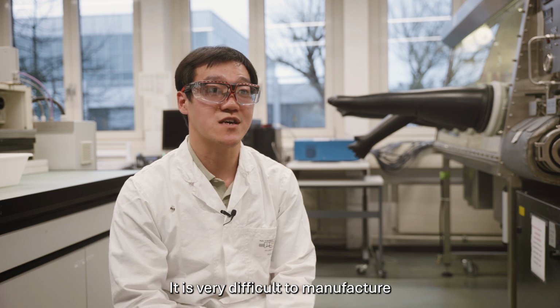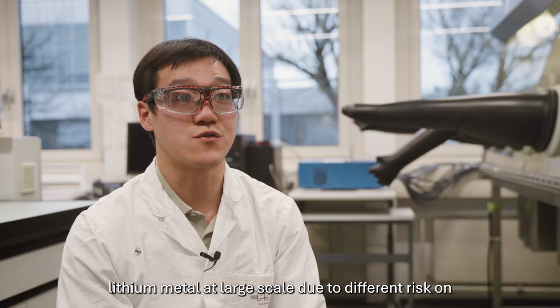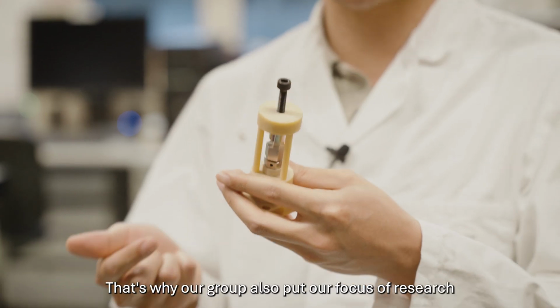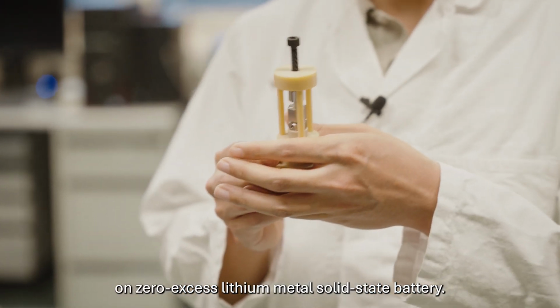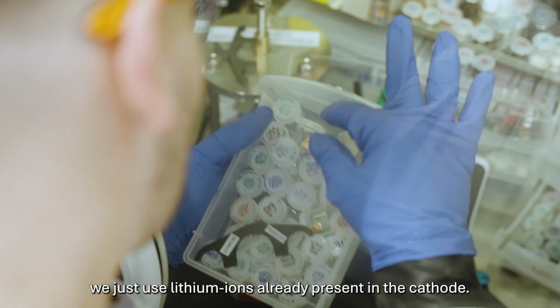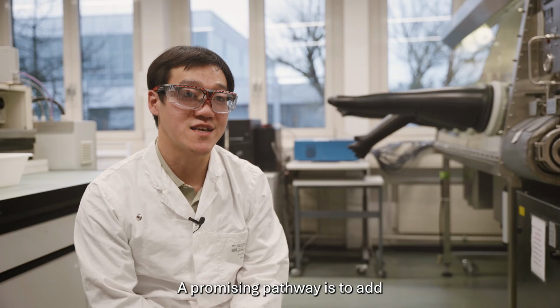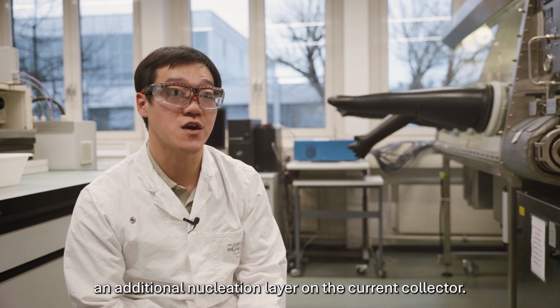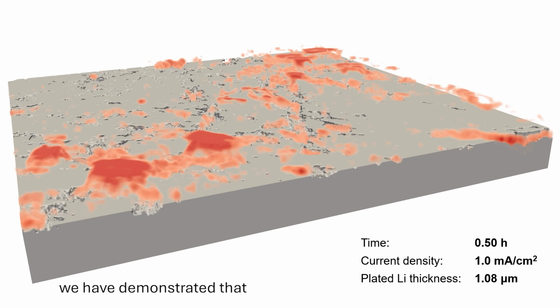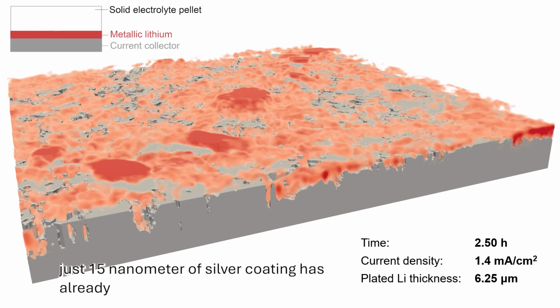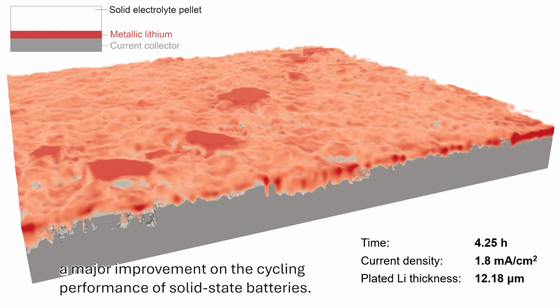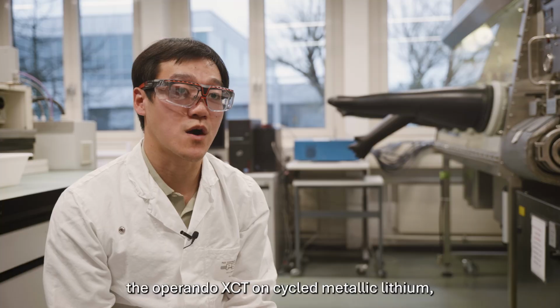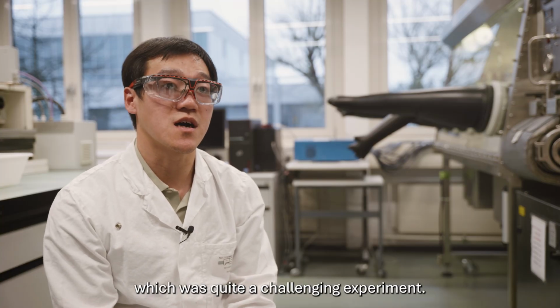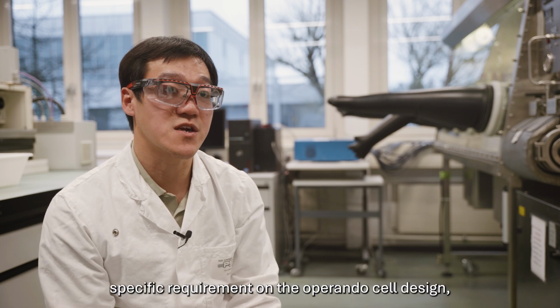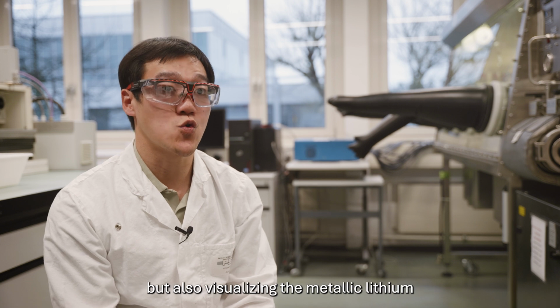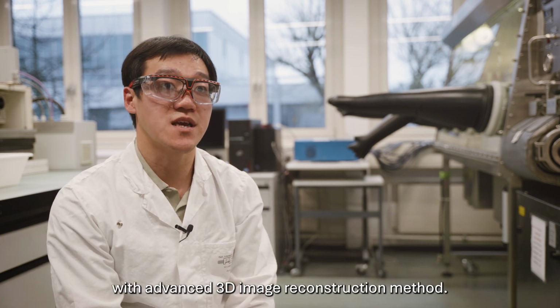It is very difficult to manufacture lithium metal at large scale due to different risks on safety and contamination and so on. That's why our group also puts research focus on zero-excess lithium metal solid-state batteries. That means we just use lithium ion already present in the cathode. A promising pathway is to add an additional nucleation layer on the current collector. In 2024, we demonstrated that just 15 nanometers of silver coating already gives a major improvement in the cycling performance of solid-state batteries. Secondly, we were able to perform operando XCT on cycled metallic lithium, which was a quite challenging experiment, not only because of the specific requirements on the operando cell design, but also visualizing the metallic lithium with advanced 3D image reconstruction methods.